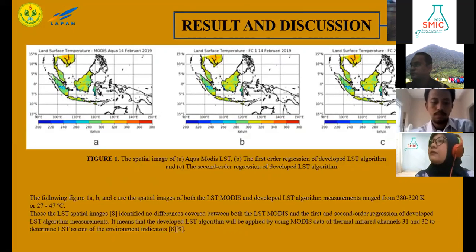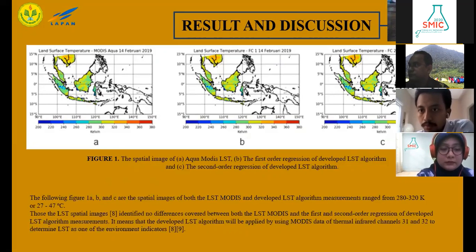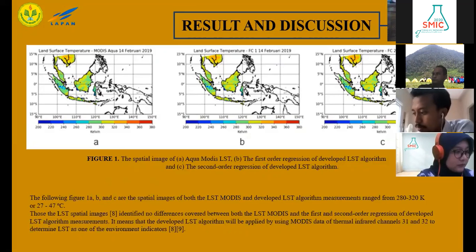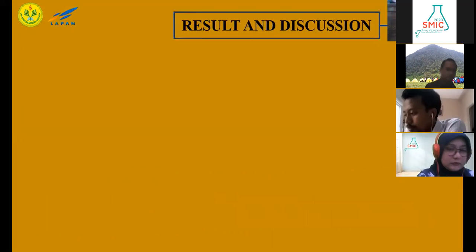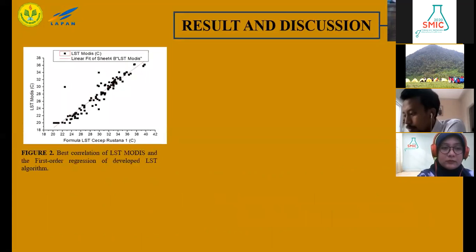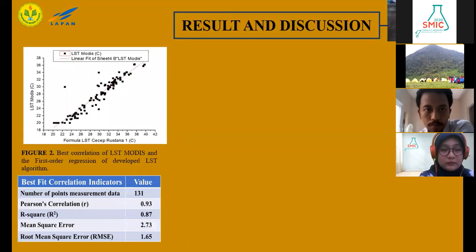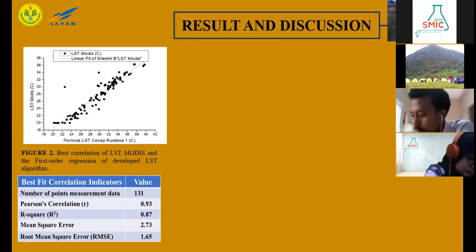It means that the developed LST algorithm will be applied by using MODIS data of thermal infrared channel 31 and 32 to determine LST as one of the environment indicators. The second factor is the best correlation of LST MODIS and the first order regression of developed LST algorithm. And in below, the best fit correlation indicators has 131 point measurement data with root mean square errors of about 1.65 and R squares of about 0.87.